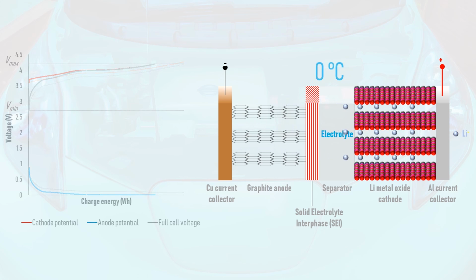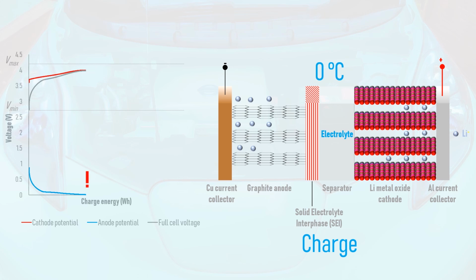At lower temperatures, however, the increased overpotential of the cell results in a decrease of the anode potential. If the rapid charging current is too high, the anode eventually reaches 0 volts versus lithium. At this point, it is no longer electrochemically favourable for the lithium ions to intercalate into the graphite structure.